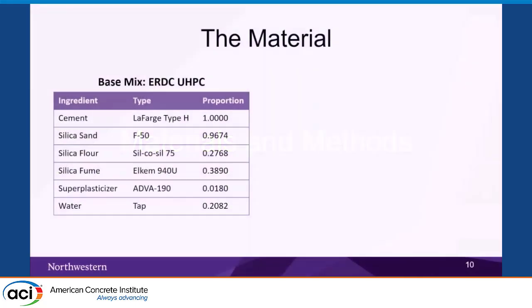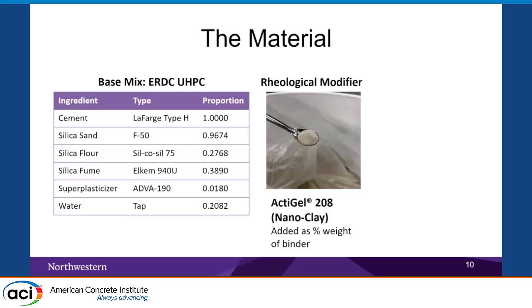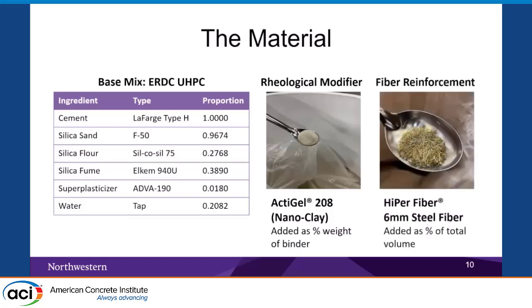For the materials and methods, we use the base mix of the ERDC UHPC mix, which consists of cement, silica sand, silica fume, silica flour, and superplasticizer. Here I used the ADVA 190 to develop this mix, and then of course we have water. We have a specific mixing procedure each time we perform this mix, and we use a rheological modifier to make it printable. We use ActiGel 208, which is nanoclay, at 0.7 percent by weight of the binder material. In this work, we used some samples without fibers and other samples with fibers, at 2% fiber by volume.